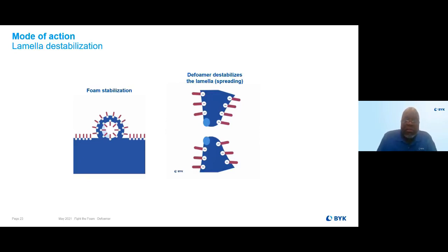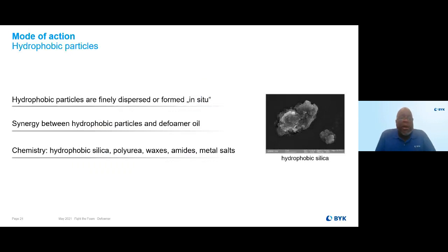And yet another, there are hydrophobic particles involved, where hydrophobic particles are dispersed throughout the defoamer along with defoamer oils and sometimes polyurea waxes and other ingredients just to stabilize it and hold it in solution.